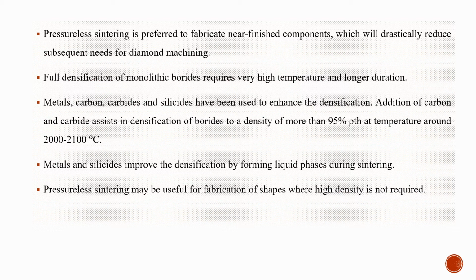Full densification of monolithic borides requires very high temperature and longer duration. Metals, carbon, carbides, and silicides have been used to enhance the densification. Addition of carbon assists in densification of borides to a density of more than 95% ρth at temperature around 2000 until 2100 degrees Celsius. Metals and silicides improve the densification by forming liquid phases during sintering. Pressureless sintering may be useful for fabrication of shapes where high density is not required.